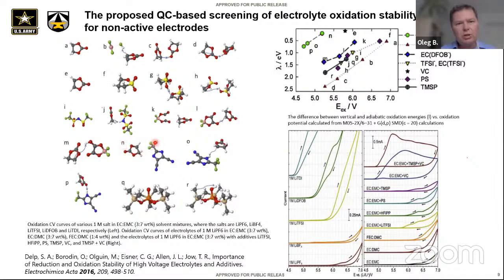In N point, we just take EC and TDI, which is a cyano-containing anion, which Michel Armand has been working a lot on. That has a pretty high oxidation potential. However, if nitrogen of the anion takes a proton, or if it takes a proton and reorients, that's point P, the stability becomes lower because EC decomposes. But it doesn't need very large reorganization energy for that. So similarly, next step, we looked at the LiBOB, lithium DFOB, these points K, L, and M. K point is here, the largest potential. Oxidation potential when its oxalate group starts expanding, the DFOB oxidizes by itself. If it oxidizes and then removes a proton and reorganizes, then points are lower. And so on, we go through screening of all electrolytes.